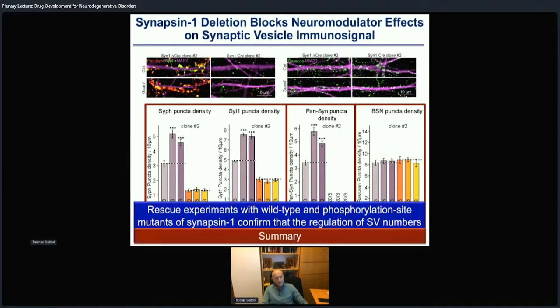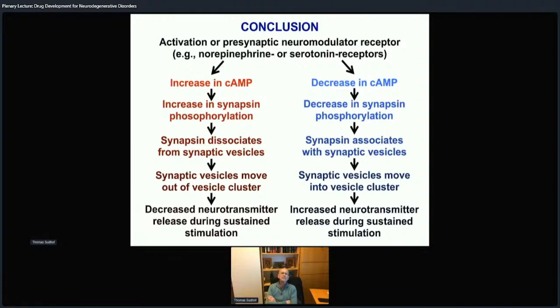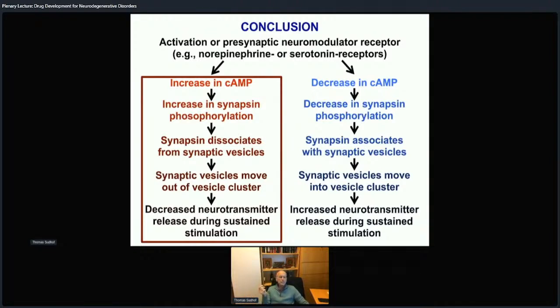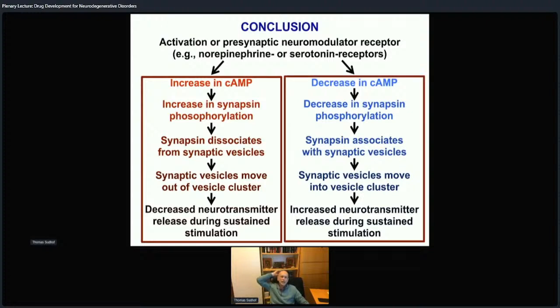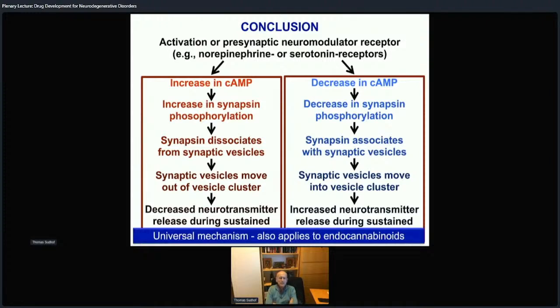So as a summary then, what I've told you here as a conclusion is that activation of presynaptic neuromodulator receptors, norepinephrine, serotonin, when they increase cyclic AMP, you cause a decrease in neurotransmitter release during sustained stimulation because you increase synapsin phosphorylation, which then causes synaptic vesicles to disperse from synaptic clusters. When you decrease cyclic AMP, you cause an increase in neurotransmitter release during sustained stimulation because of the opposite effect, because of a decrease in synapsin phosphorylation causing an increase in synaptic vesicle numbers. Thus, this is a universal mechanism that regulates in a novel way how synapses function.